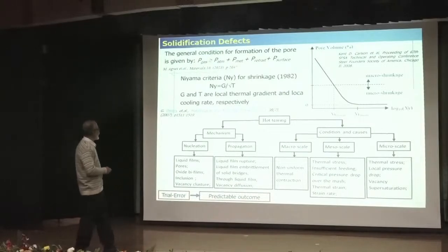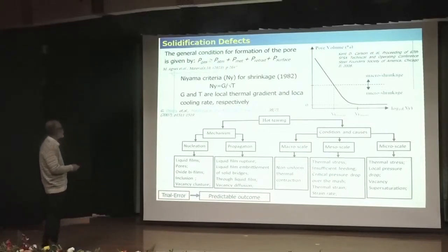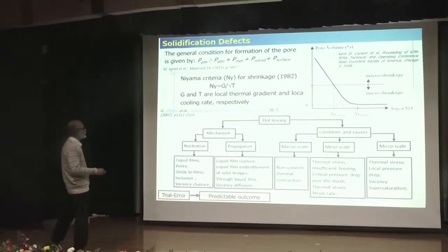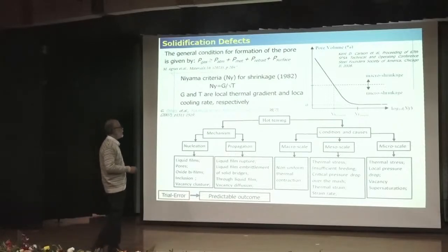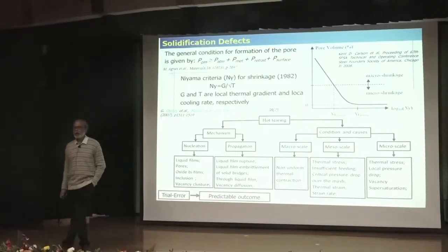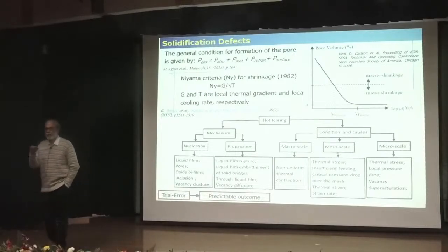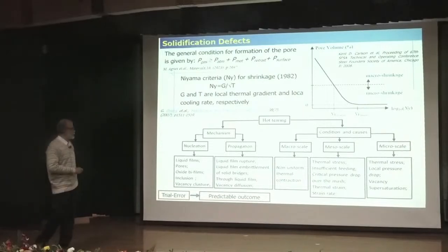Niyama proposed a criterion in this form where G is the local thermal gradient, and T is the cooling rate. So if you plot the Niyama criterion, you can find different values where there is no shrinkage, there is micro shrinkage, and there is macro shrinkage. So empirically, you can predict the occurrence of the kind of shrinkage during the solidification in a mushy state.